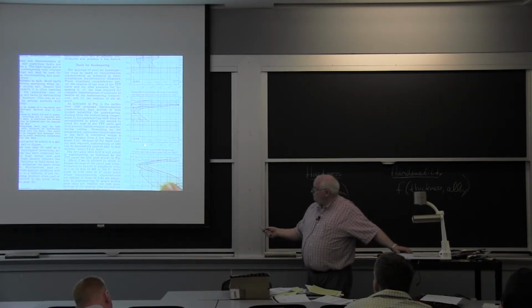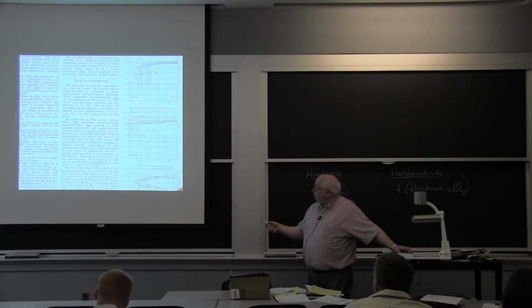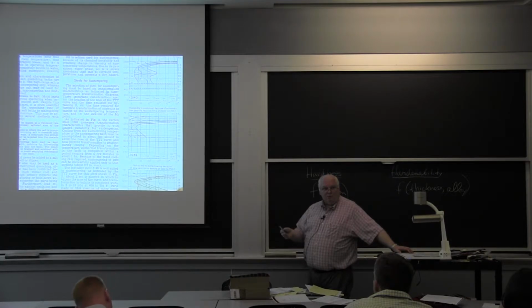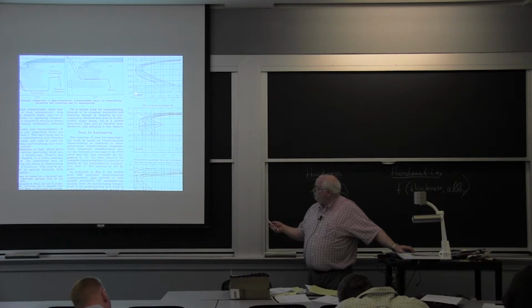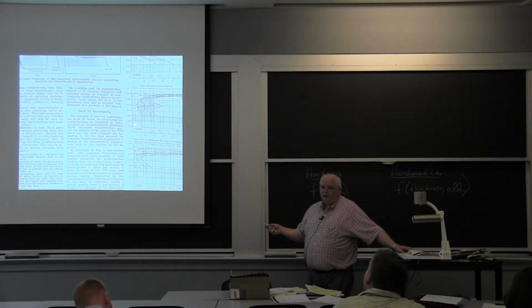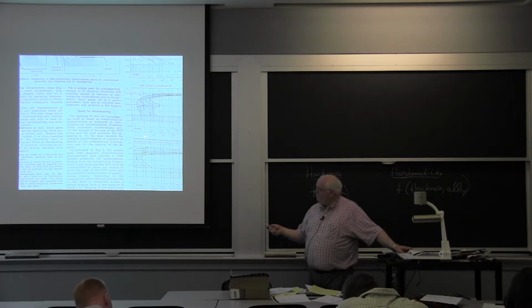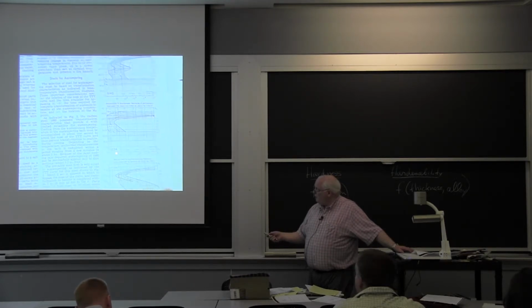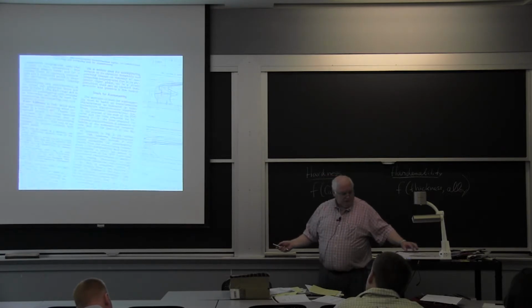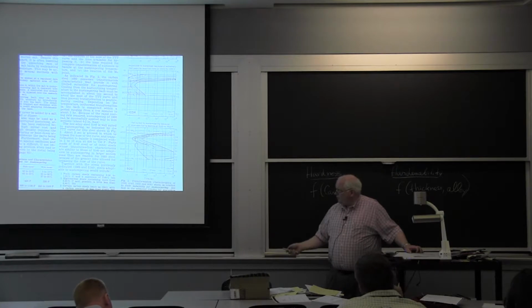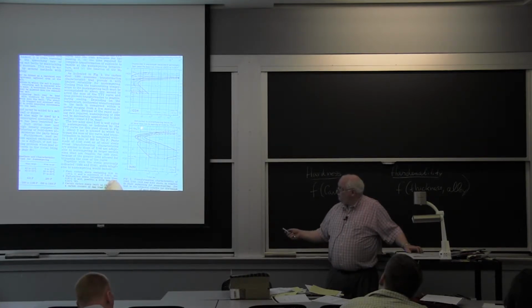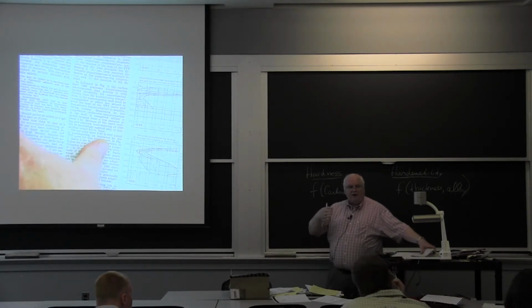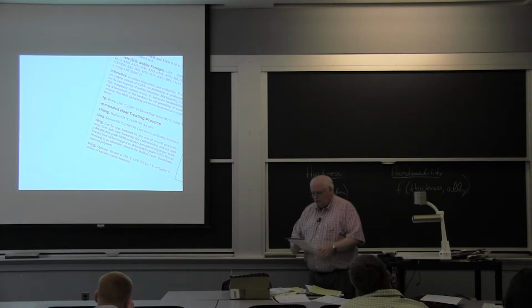The last 2 numbers, the 34 means it's got 0.34 carbon. The 40 means it's got 0.4 carbon. So the last 2 numbers are the hundredths of a percent carbon, and the first 2 numbers basically tell you whether it's alloyed or not. So a 1080 steel, carbon steel, 0.8% carbon. Okay, 5140 alloy steel. I got to go look it up. I don't remember. There are hundreds and hundreds, if not, well, there are really thousands of steels. But you control the carbon content, which are the last 2 numbers, and they've given you various ones here, 0.61 carbon, and the second number will also tell you where in the series you are, whether you're high nickel or high chrome or whatever.